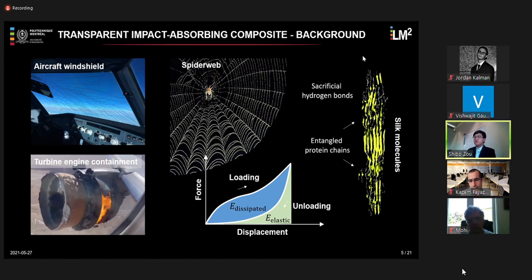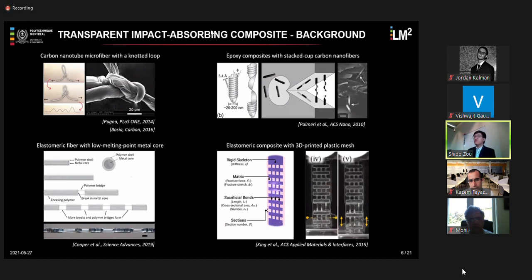So in the literature, there already exist a few examples where people try to make this sacrificial bond structure in the micro or nanostructure of the engineered materials. The first example shown here, the researcher made a knot along this carbon nanotube microfiber. Under stretching, the length hidden by the knot will be released, and the energy is dissipated by the friction during the releasing of this knot. And this increases a lot of the toughness, the energy absorption of this single fiber.